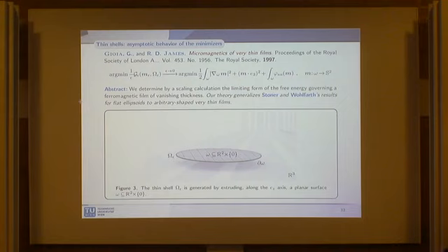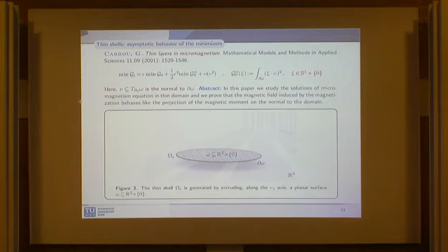And what happens is that if you go to the next order in the gamma expansion, so if you want to have more information about the minimizer, you discover that the expansion goes like this. At the zeroth order, although there is this epsilon, you get the model that we saw before, and then at the next order you have to minimize this quantity, where psi now is an in-plane vector and nu is the normal to the boundary of this domain. So among all possible in-plane configurations, the energy will select the minimizer which minimizes this energy function.